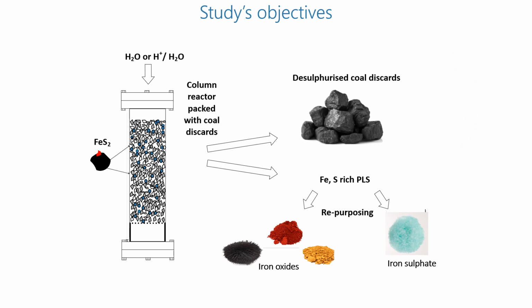In this study, proof-of-concept experiments were performed in laboratory-scale columns over 380 days to assess the feasibility of heap bioleaching as a sustainable disposal strategy for sulfur-bearing coal discard. Coal discard from Mpumalanga in South Africa containing 10% pyritic sulfur was used. The iron and sulfur-rich leachate generated can potentially be repurposed to recover valuable products such as iron oxide or iron sulfate.